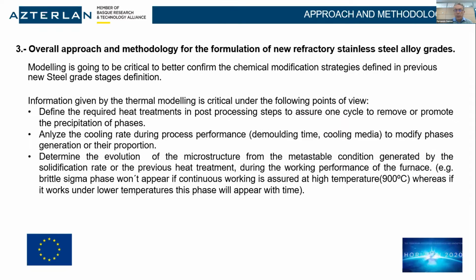Well, why is the information that modeling is giving us so critical? It defines quite clearly the required heat treatments in post-processing steps to assure one cycle to remove or promote the precipitation of phases. We are going to use that to fix the heat treatment temperature. Depending on these ranges of chemical composition, it is going to tell us when these phases are going to precipitate, and we can assure the temperature of heat treatment.